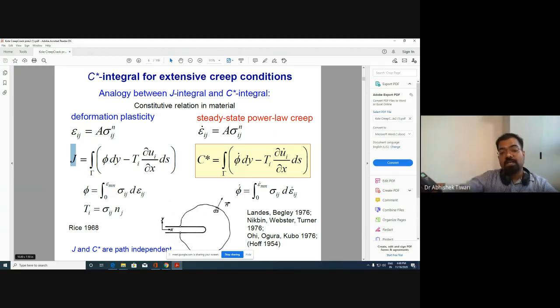Now in creep, power law creep, we have a cousin of the J integral. The problem you will realize is that this is not coming from any theoretical background. If there is any time dependence of J, then that should have come in the form of the differential of J with respect to time. So it should have been dJ by dt, but you see that this is not equal to dJ by dt, because the second part will have a second term where the traction derivative should also be there if you're trying to differentiate the J integral with respect to time. So this is not dJ by dt. Don't get confused with that. What is happening in a steady state condition is that the strain rate is following a power law.